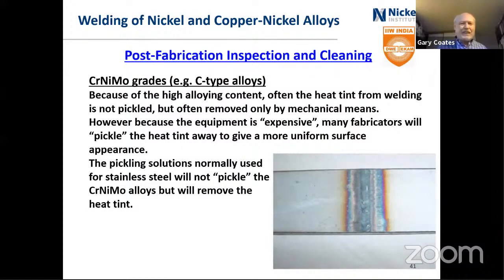However, because the equipment is expensive, your fabricator, your customer is paying a lot of money for this equipment, and they want to have it really look good. You want it to look good. So often they will put the pickling paste on the welds, and that does pickle away the heat tint. However, it really doesn't pickle the material underneath. Like with stainless steels, pickling paste will actually remove a layer of stainless steel, a few atoms worth. It doesn't actually do that with these chrome nickel moly alloys, the C alloys, but it makes it look good and more uniform in appearance.